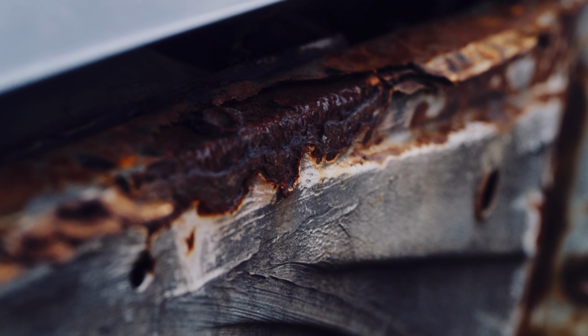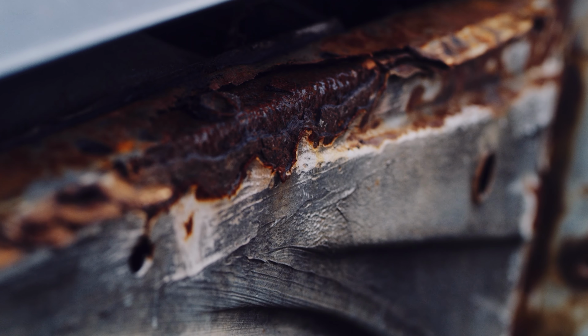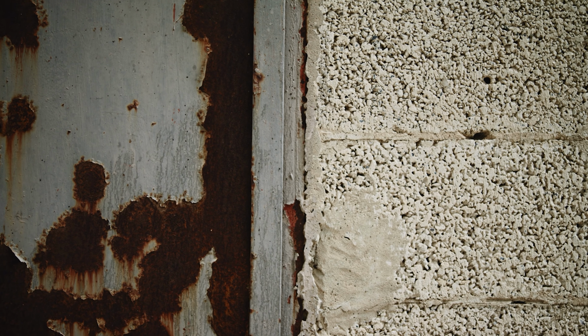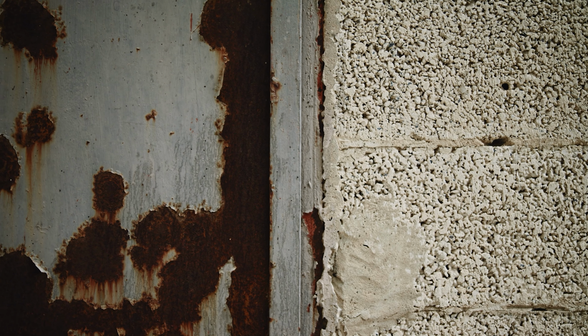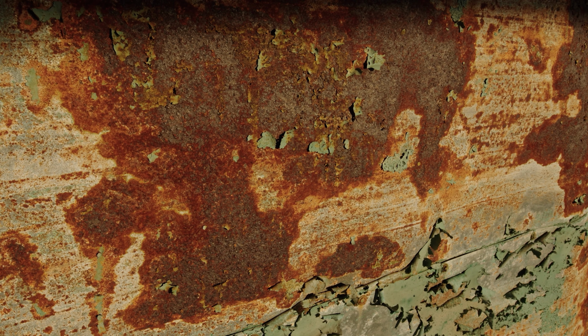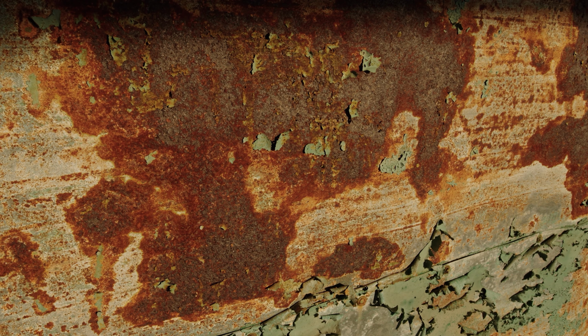Now to hit those fire rating numbers, safe manufacturers line their safes with drywall, gypsum board. The moisture in the gypsum absorbs heat and turns to steam, which works great in an oven test. In real fires, the outer steel heats up way too fast, and the benefits disappear. Worse, the drywall creates a corrosive environment inside your safe, releasing moisture and sulfur compounds. That's why the industry sells millions of dollars a year in anti-corrosion products.